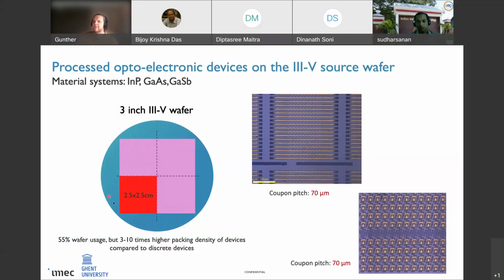So here you see a schematic of a 3-inch wafer on which you can fabricate your III-V source devices. Now, if you assume that we are using a 1-inch by 1-inch stamp, that means effectively we can use this pink square of the III-V wafer to pick up and print components from a III-V source wafer to a silicon target wafer. So if you do the calculation, that leads to a wafer usage of only about 55% in this case, assuming, of course, you take the biggest possible stamp of 1 inch by 1 inch.